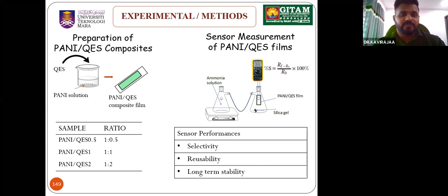For the preparation of the composite material, we carried out an ex situ method, which means the polyaniline was already prepared, and then we physically added the eggshells and blended it. After that, we prepared a few ratios as shown in the table. For the sensor measurement, we used a multimeter, and then we used the formula as shown in the slide. We also carried out a few sensor property measurements. Next slide.